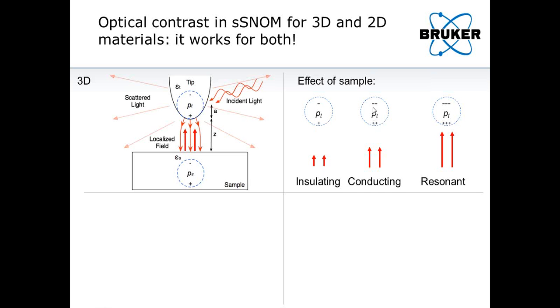If the sample is conducting, you get a little bit more. And if it's a resonant sample directly underneath the tip, then your reflection can be potentially higher than the conducting case, and you will drive a lot more charges to the dipole.